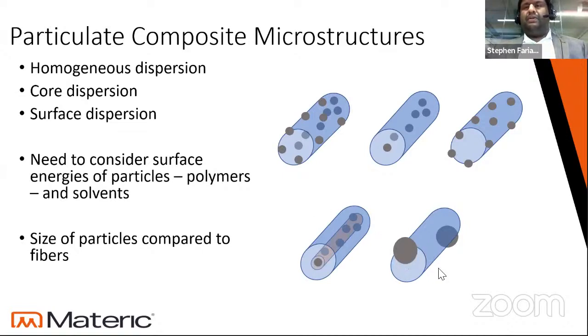the particles compared to the fiber diameter size. They can influence each other, and if the particle is very, very small compared to the fiber diameter, then maybe you can guarantee it's going to be fully interior. But if it's large compared to your fiber diameter, it's just not geometrically going to fit into that space.